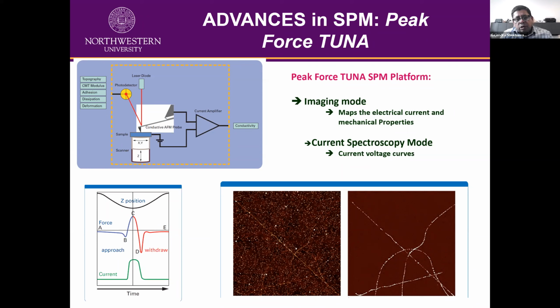So you can see here at the bottom left figure, this is the maximum force you can see at position C, where the force on the sample is at its maximum, so you can see a large current. So you can get a peak force current. The image on the left is a topography image of carbon nanotubes, with a lot of nanoparticles there.